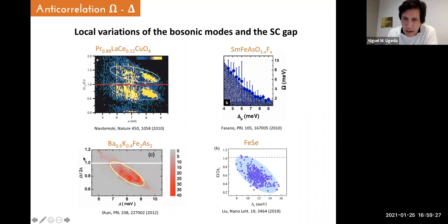All of the plots are in general divided by two delta, and the reason is because within the theoretical framework, it should not only show a correlation, but all these values should be below 2 delta, meaning that the binding energy of this collective mode has to be lower than that of the Cooper pair. Okay, and as you can see in all these examples, this ratio is below one, in our case as well in general, but all these works